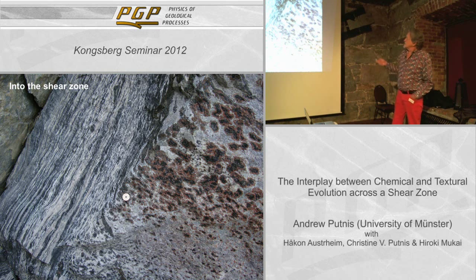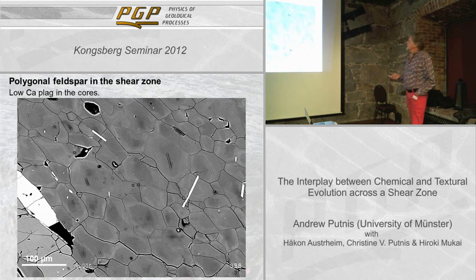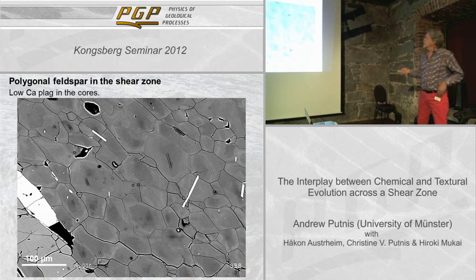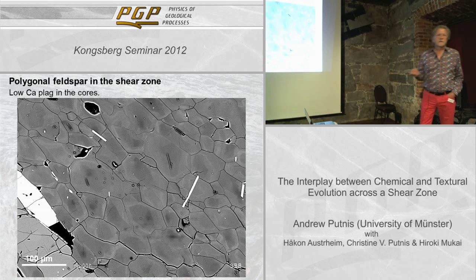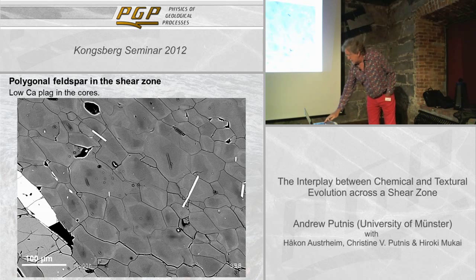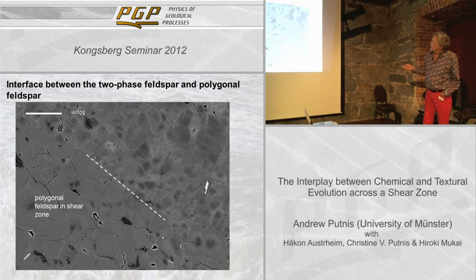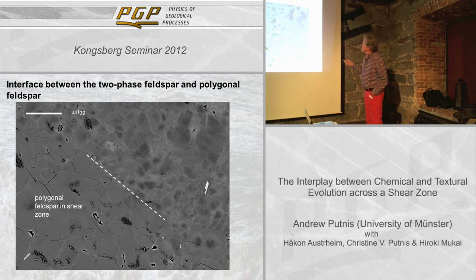So the interpretation here is that we've had some fluid infiltration, we have a phase separation — could be a coarsening of this nanoscale exsolution intergrowth — and already this fragmentation is a potential weakening mechanism. Let's go back to the shear zone. Whenever you take a thin section of anything over here, you find lots of little shear zones. In the shear zone we see a polygonal, foam texture — it's often called that in material science — it's an equilibrium texture that happens when things just grow from a fluid. We also see that it's got some chemical zoning.